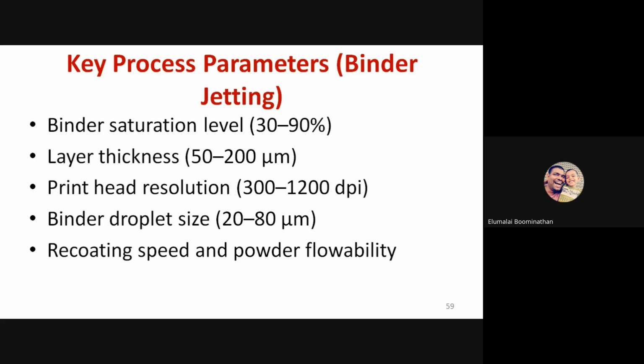If the droplet is very small in size, it won't penetrate enough, it won't spread enough. If the droplet is a very large chunk, it may create a crater, it may eject the powder from the build platform. And we also have print resolution, recoating speed, all those parameters are also very vital to ensure the quality and the mechanical property of the build product.